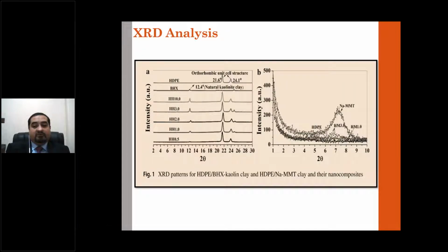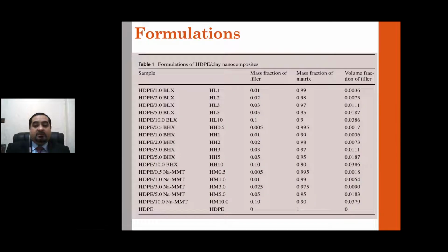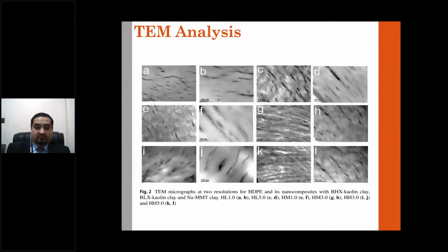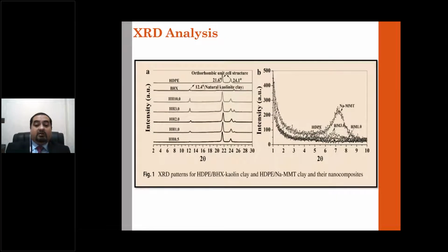Now, one of the first analyses that is done in characterizing nanocomposites is XRD analysis. And from here, you can see that due to the internal structure of kaolin clay, it becomes really difficult for us to separate the individual layers. But sodium MMT clay can be differentiated.